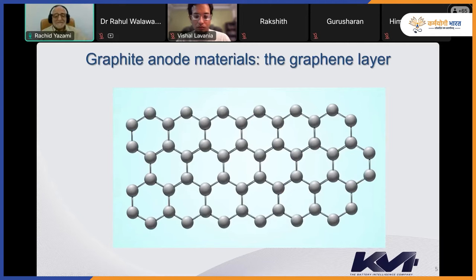Graphite. So the graphite is, as in the introduction, Dr. Rahul and Vishal said, my invention. Yes, graphite. The lithium intercalation into graphite was known since the 60s, but it was chemical intercalation, not electrochemical. What I brought, I was the first to show that we can intercalate lithium ions between the graphene layers. You can see the graphene layers, the small balls are carbon. It's a monoatomic structure. It has only carbon, and carbon atoms are organized within the graphene layer in a honeycomb structure. You can see the hexagons of carbon atoms. And then this is one layer, which we call the graphene.